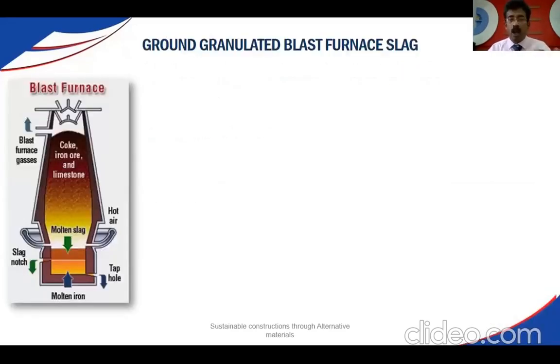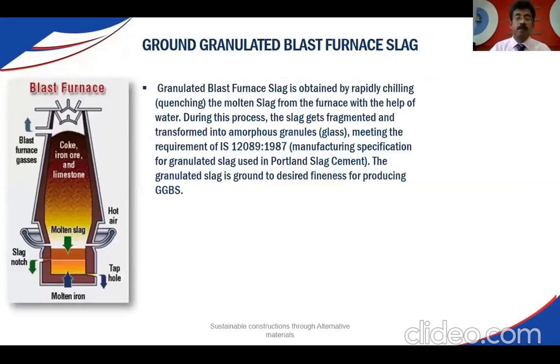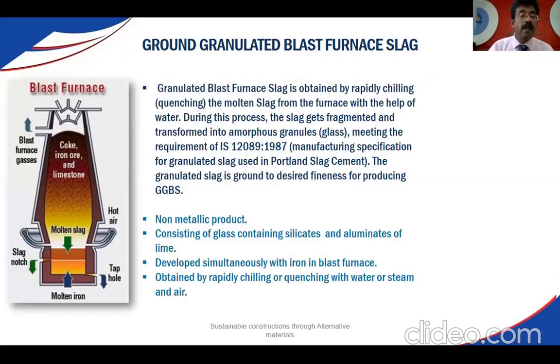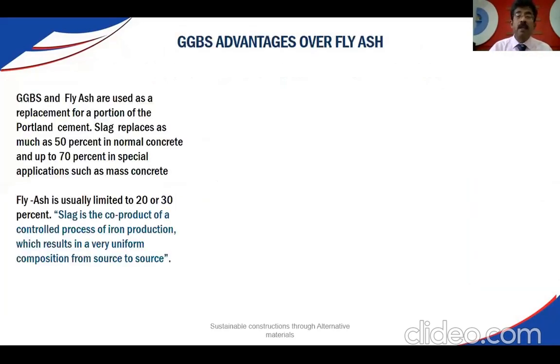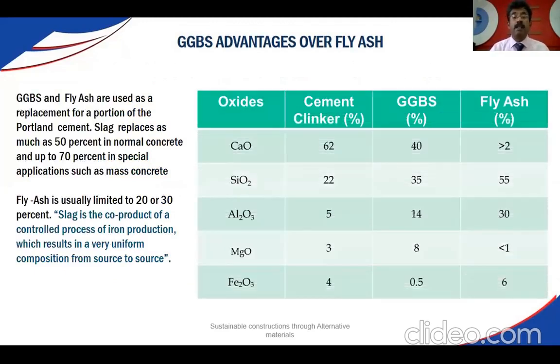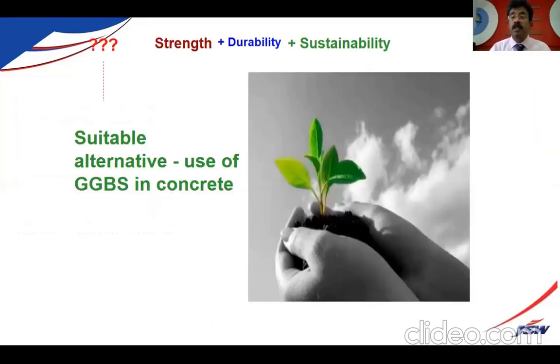So I'm coming to the ground granulated blast furnace slag, which is a cement replacement. This is a product of the steel industry from the hot metal. So it is coming from the blast furnace. We know very well molten slag, and we generate this. It is better than fly ash because it has both calcium oxide and silicon dioxide. GGBS slag has 40% calcium oxide, when cement has 62%, and we have 35% silicon dioxide. So it's just like cement only. Okay. If you add water and mix it with concrete, then it reacts with cement. The process makes it strong, durable, and sustainable using GGBS.